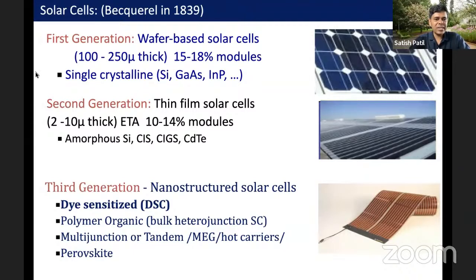So you use less material to harvest more light when you switch from first generation to second generation. This is the major advantage, but in return, the lifetime is very poor for all these other materials, whereas silicon solar cells are very robust, with 25 years of lifetime. When you switch to thin film solar cells, you gain over some of the limitations, but you face other limitations. So that has been a challenge and ongoing work in the community working on solar cells.